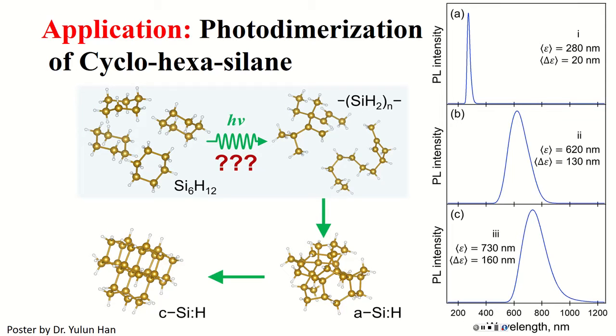So why don't we try to see if the excitation can help polymerization, or if you want to be conservative, dimerization of these precursors. With understanding that if this reaction goes far enough, finally it will generate silicon nanostructures like quantum dots, thin films, nanorods. And the natural intuitive expectation is that if we start from small size precursor molecules, they would have spectra in the UV range, and as soon as association and polymerization goes on, it shifts to the reddish part of the spectrum.